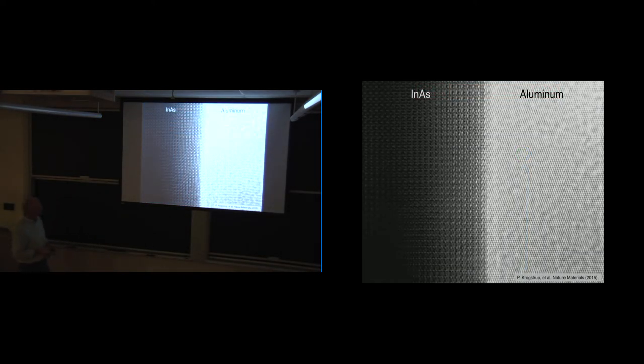And here's a picture of that remarkable thing, which is the interface crystallizes. So here is aluminum and indium arsenide epitaxially matched. Now, if you haven't seen this before, you should be having a heart attack right now, because they're not lattice matched. They're not the same lattice constant. Why has aluminum crystallized with indium arsenide?